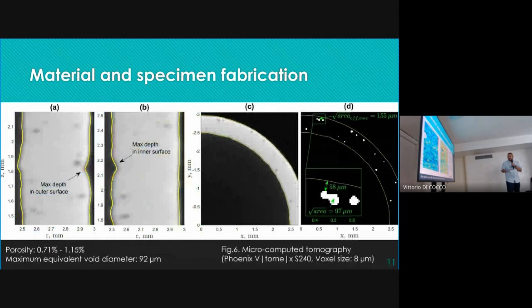We also did tomography scans of the specimens, firstly to accurately measure the specimens, the thickness and things like that, and to look for the pores. The porosity of the material was between 0.7 and 1.15%, so not so bad. And you can see the valleys here: B is on the inner surface, and on the left you can see the outer surface.